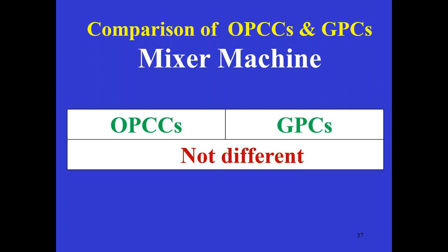And I saw a good mixer machine in the Malaysian laboratory of Unimap at Perlis. Again, their mixer machine is so good. So with little liquid, they are able to make the concrete flow. Same thing happens in Dr. V. Rangan's laboratory at Curtin University in Australia. And also wherever V.K. Malhotra worked in Canada on high performance concrete and high volume fly ash concrete, their water binder ratios are very small. Still, they are getting workability. One of the main reasons is their mixer machine.